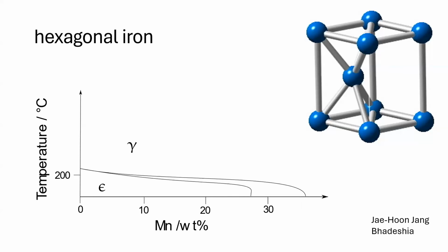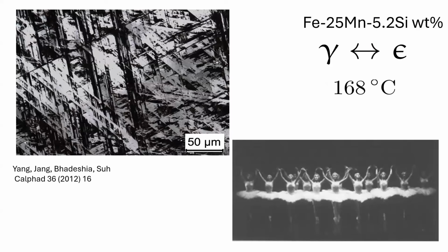Now, I'm going to show you things which we have tried very hard and not succeeded, because you mustn't go away with the impression that everything works. I'm going to show you two examples. So this is the hexagonal form of iron, and we can make it under ambient pressure by alloying. In order to get a transformation from the austenite to the hexagonal iron, it would have to happen at temperatures below 200 degrees centigrade. The only way you can get that to happen is by deforming the atoms in a choreographed manner like ballet dancers. So they all move together. In other words, like martensite, all right?